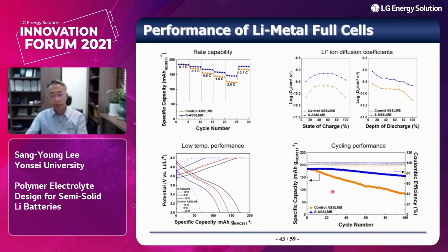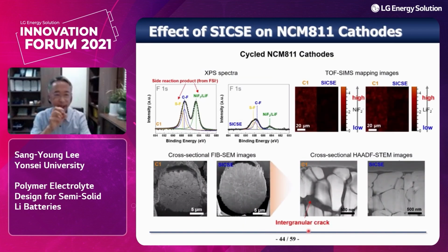Okay, and then in comparison to the control cell, our single ion conductor can provide superior cycling performance. To understand this better cycling performance, we have examined what is happening on the cathode side. So this result was obtained from the cycled NCM811 cathode. As you can see, for the control cell, you can find that side reaction product was formed. However, in our case, the side reaction was significantly prevented due to our single ion conducting electrolyte,